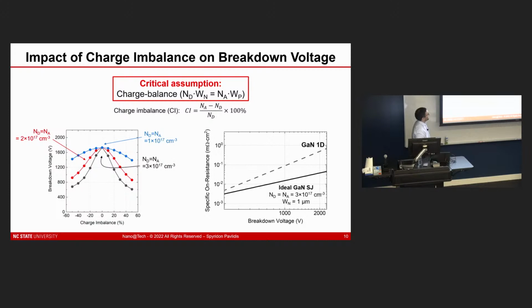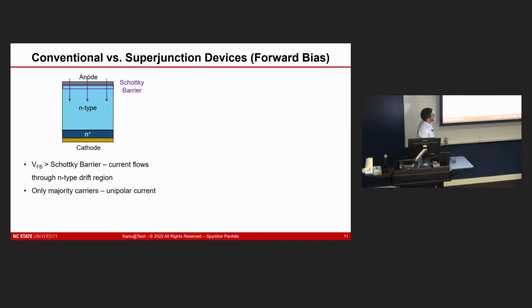So this really places a critical need on doping, and then being able to control doping in both of those P and N regions side by side. And you can see another consequence of that happening here. If I start to see charge imbalance happen, I start to move more to a 1D case, and I can see a very significant reduction in my breakdown voltage, and basically a complete collapse of the superjunction feature that you get with these devices.